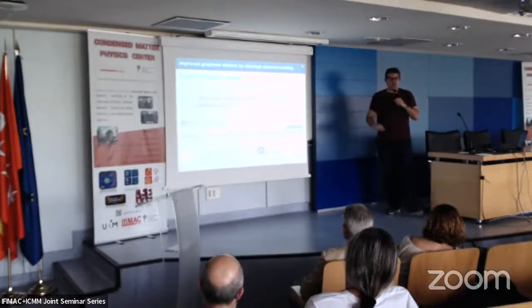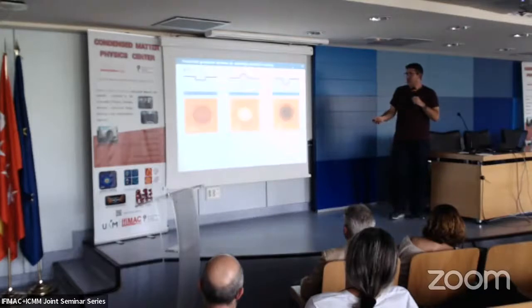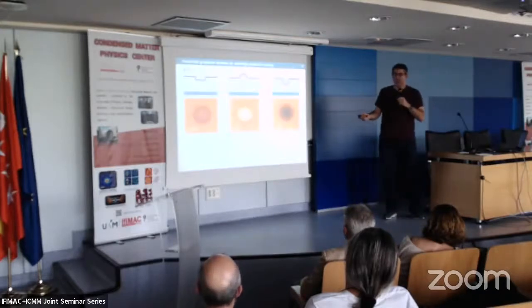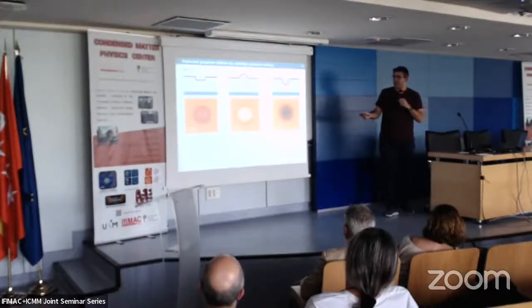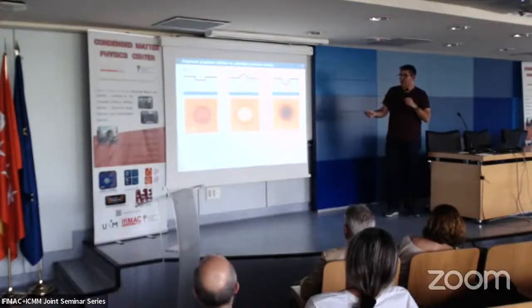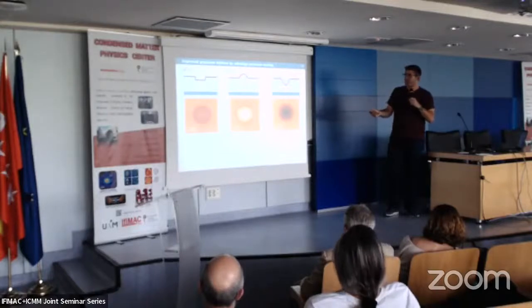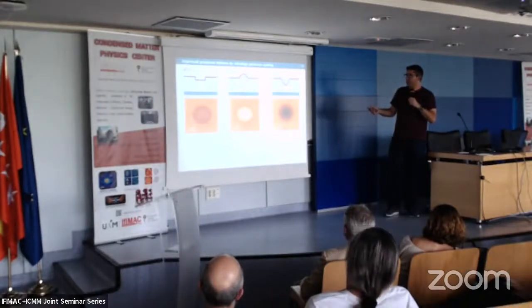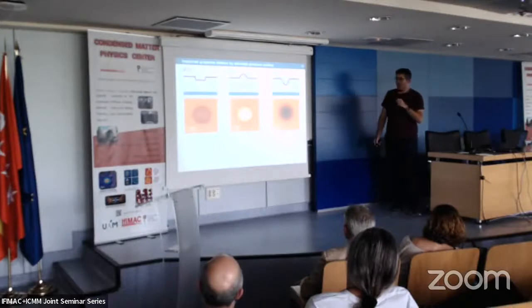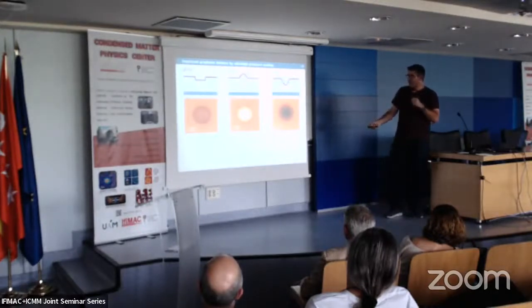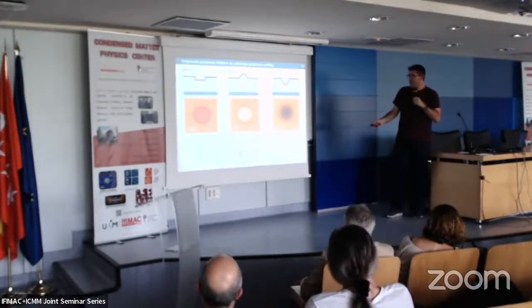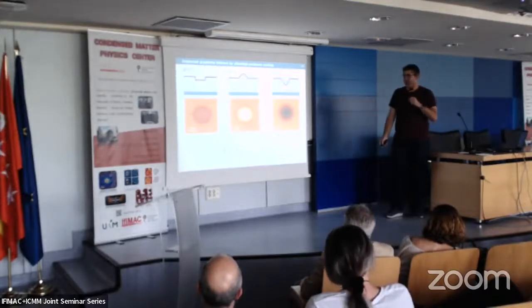Okay, so I will jump now to the other part in which we studied the modification of graphene properties, in this case, mechanical properties. Okay, so in this case, we studied this kind of devices, which we are also very familiar with in the lab, to study mechanical properties of graphene. We put graphene on top of a hole in silicon dioxide, and in the lab there is a lot of experience of coming with the tip and just pushing it and studying the mechanical response, but also a lot of experience in changing the pressures inside and outside these blisters to then study how they inflate and deflate, and this will also give us information on the mechanical properties. So by doing this inflation, deflation, we can then study the variation of the height of these blisters with time and obtain characteristic decay times.